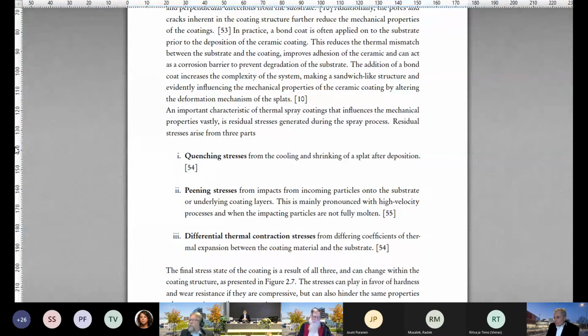Yes. Well, there is, of course, the thermal effect from the quenching, as is the first part. And the splat will have some property as it first arrives, and it will, of course, be altered by the consequent splats that come after that. In this case, it's peening stress. Like mentioned here, with ceramics it's not seen as such a big effect because they are already quite solid and hard. They wouldn't deform so much, so potentially they could crack from the incoming particles. And finally, the thermal contraction comes from the difference in thermal expansion of the substrate and the coating. Did I miss the question, or do you look puzzled? Well, I think those are the issues.